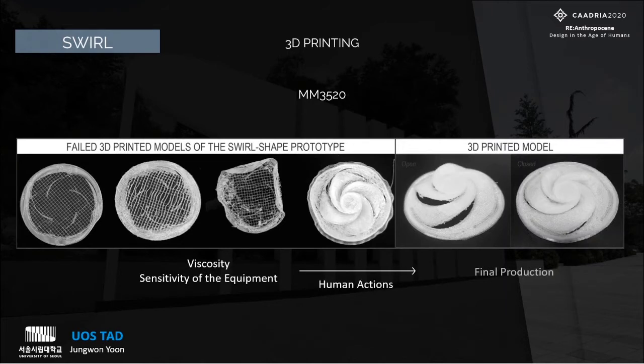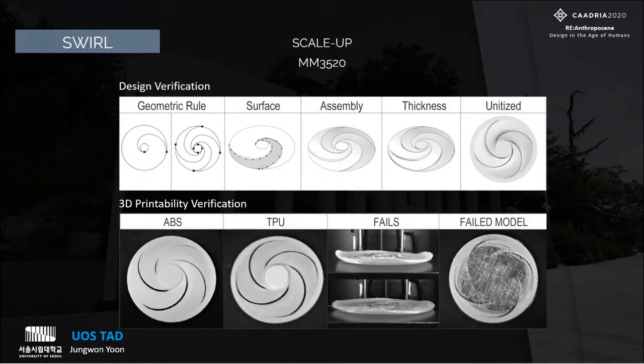Due to the viscosity of a hot melt SMP and sensitivity of the printer, the process was halted many times. However, by human handling actions to prevent the SMP clog in the nozzle and recognition errors against the filament, the final production could be accomplished. However, in scaling up the model size from 100 mm to 150 mm, previously unknown matters stood out. After failure in 3D printing, the design model was reviewed and fixed.